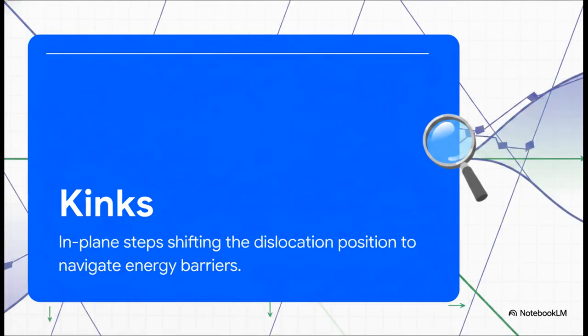Conversely, we have kinks. Now, these are your in-plane steps. They shift the dislocation's position, but they remain entirely within that original slip plane. So instead of forcing a rigid line over those atomic energy peaks, what we call the Peierls-Nabarro barrier, all at once, kinks actually allow the dislocation to slither forward incrementally. So they don't hinder glide at all. They actually actively assist it.